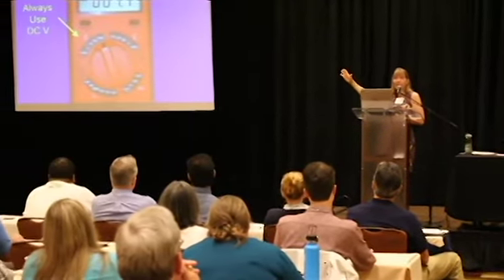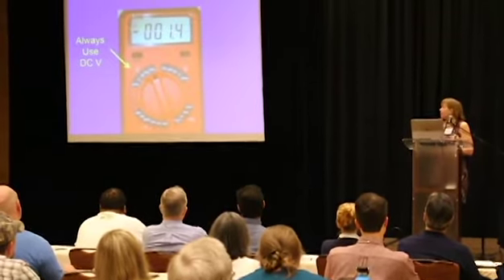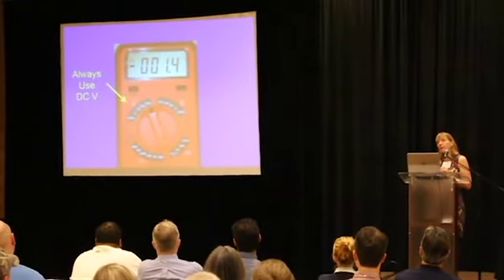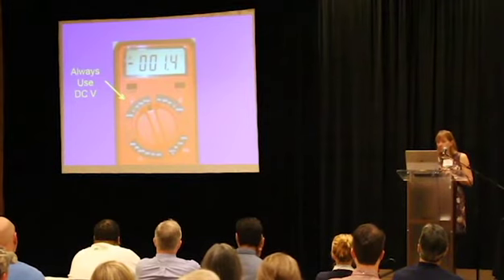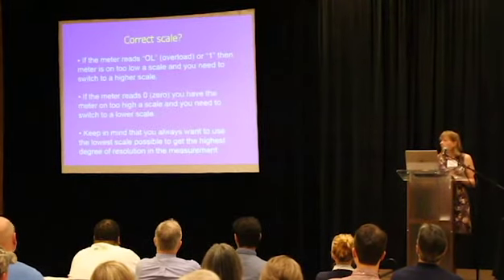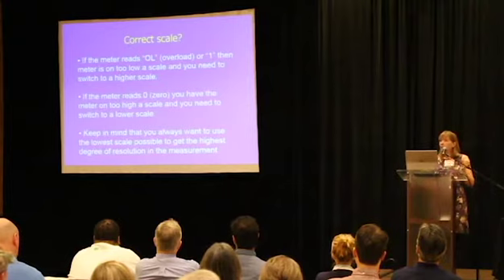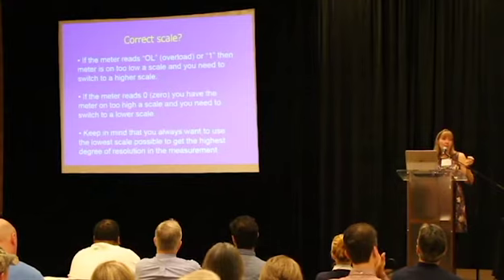So as I said, we're always going to use DC volts. If you're out in the field watching somebody, you want them to put it on the lowest setting possible. Because when they see negative 1.4, if they keep switching that dial down a little bit more, they can actually get a different number. So you want the highest resolution on that meter that you can get. And by doing that, you're going to remove one of the sources of possible errors, and you're going to have the most precise measurements you can.